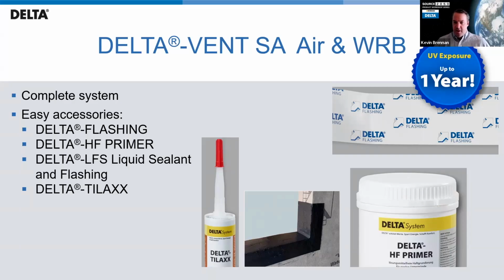Primer. Always check and see if you need primer. Some substrates need primer, some substrates don't, but depending on your application, just read the technical documents and go through it. I can tell you right now, all our third-party testing, we do our testing without primer, but please recognize that this is in a perfect lab environment. You will only get better results if you use primer, but we can't account for job site conditions. So how cold the substrate is, how well the product is rolled, how dusty the substrate is. And dust is probably the single biggest obstacle that we encounter. Well, wet substrates is probably the biggest, but short of that is dust.